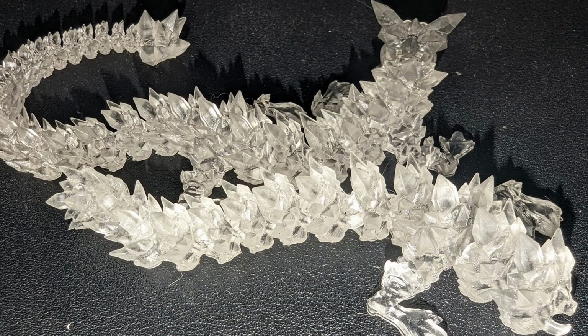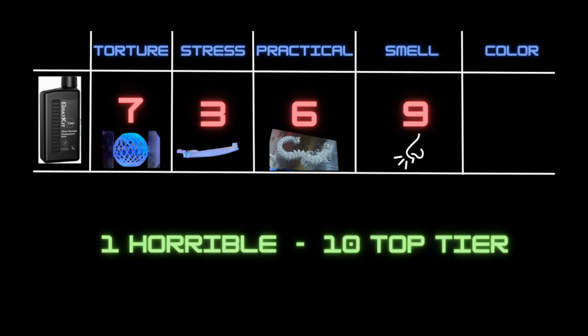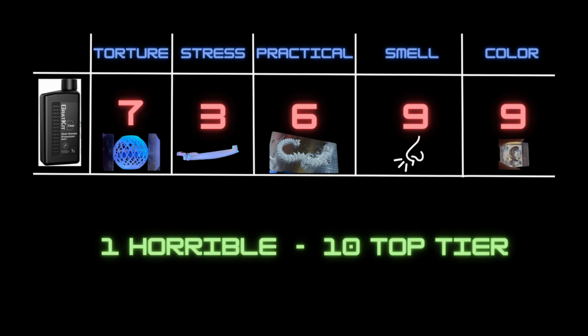In this example, I have both the solid dragon that was printed with a standard cure time and the dragon piece, which was cured for over a week. You can see that the color difference on these is fairly negligible. There is some slight difference as far as clarity on the print, and that's mainly due to the type of cleaning that was done on the solid one versus the flexible pieces. So for the score for color, I would rate this as a solid 9. It maintained its color better than just about any transparent resin I've tried so far.